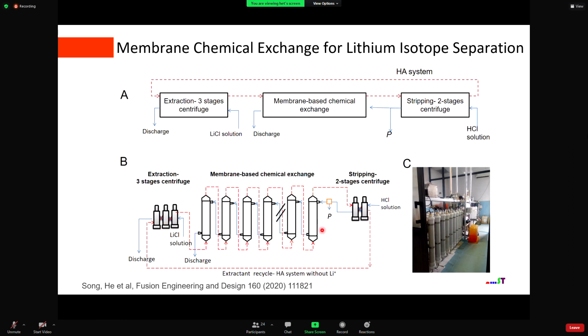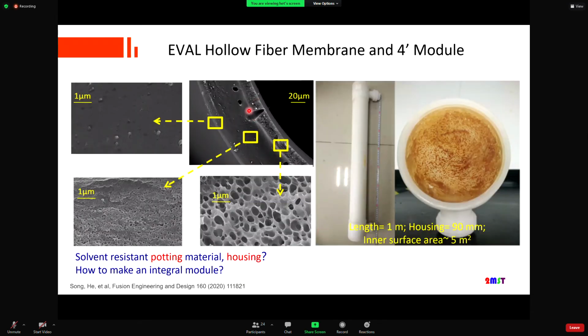The middle part is the main part of the system. We use a hollow fiber EVAL membrane module. The hollow fiber membrane, as shown here, is about 100 micron thick. It has pores, which are not really optimized, but fortunately, the diffusion of the lithium isotopes in the system is very slow. This is the module we developed in our lab. It is about 1 meter long, with a diameter of 90 millimeters. It has a 5 square meter inner surface area.